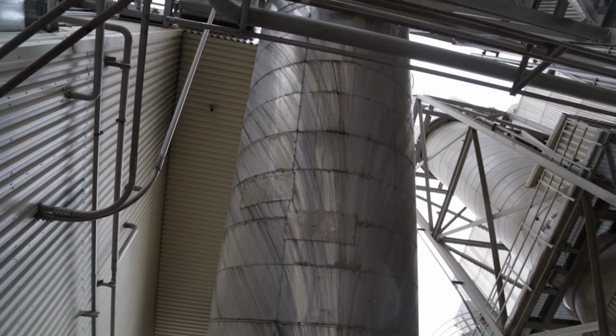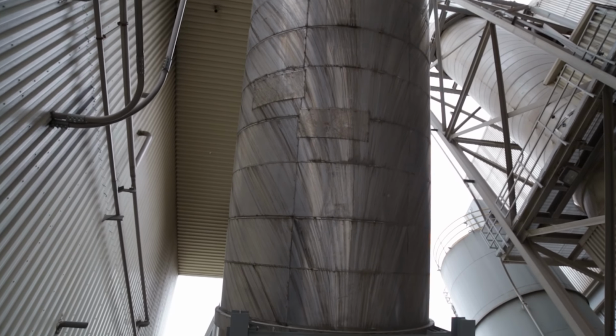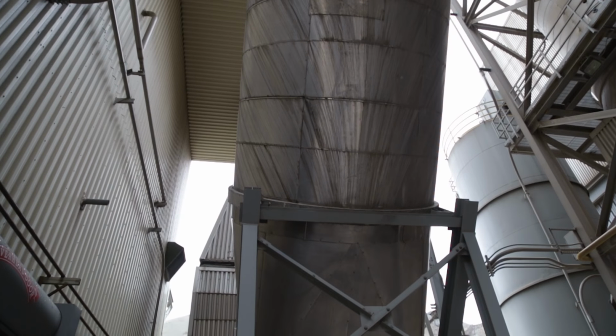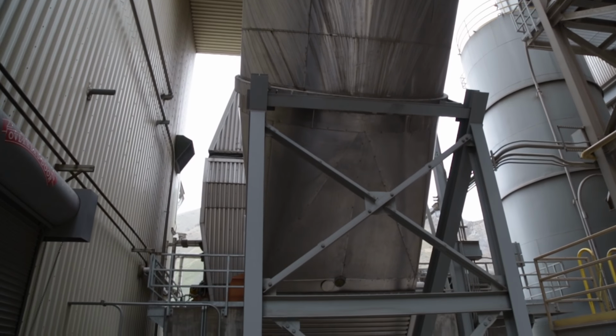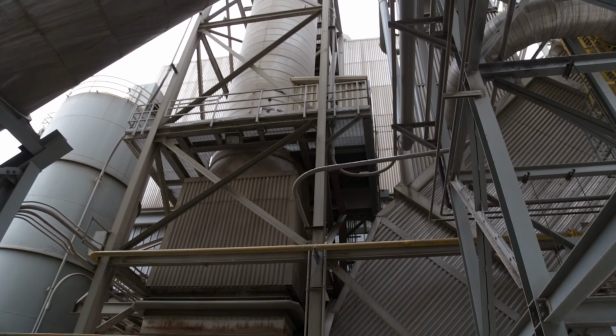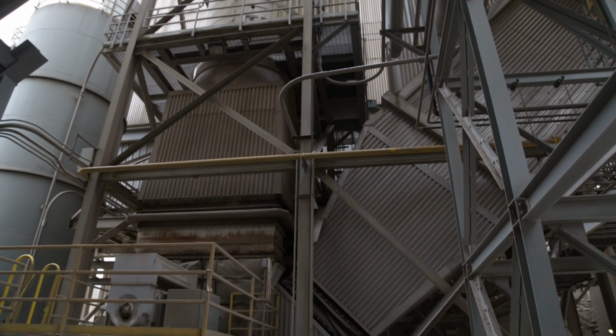Our mercury reduction system was installed voluntarily in 2010, and it reduces the output of mercuric gases by 98% from our plant. The system meets the federal standards for mercury control. The way the system works is after the kiln, the gases from the kiln go through the main baghouse and then through the mercury baghouse, which has powder activated carbon in it, which then collects the mercury. From there, the gases go up the stack, minus the mercury.